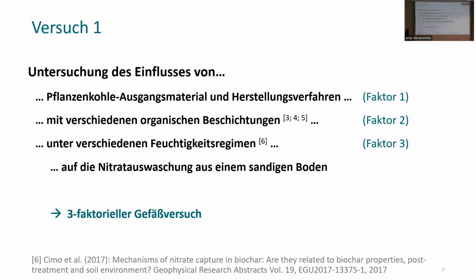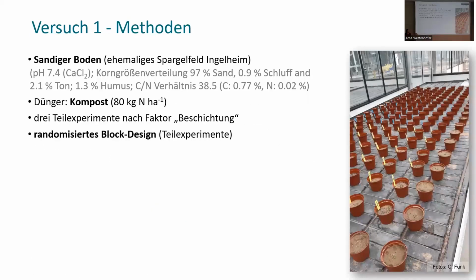In the first experiment, we investigated the influence of biochar feedstock and the production process with various organic coatings under different moisture regimes in the soil, dry soil, changing soil that's dry at times and most humid at other times, and the influence on nitrate leaching from a sandy soil, the soil we have where I study. So this is a three-factor pot trial.